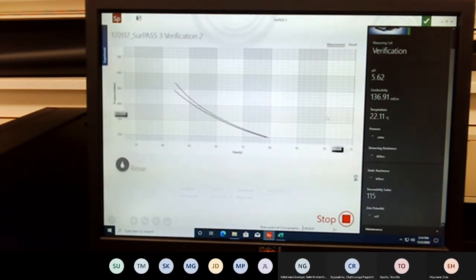And then it's starting the last measurement now, or the last rinse. So the permeability went up from 114 to 115. That's more or less ideal. You want it to be pretty close to what the previous value is. You don't want to see large changes in permeability or gap height, again, depending on which cell you're using.